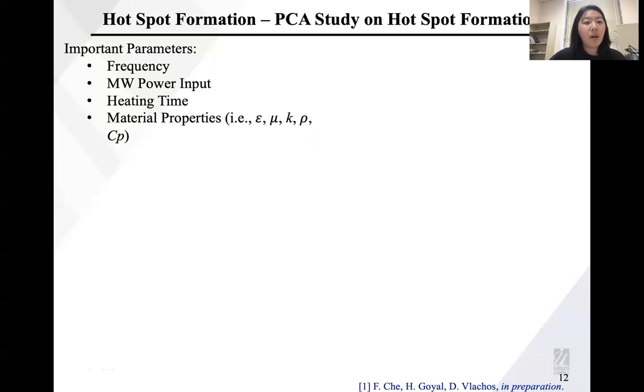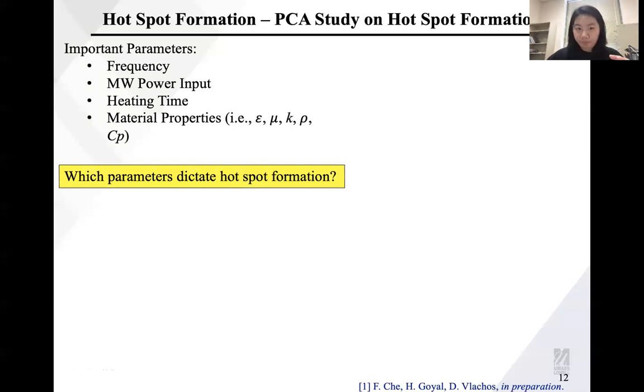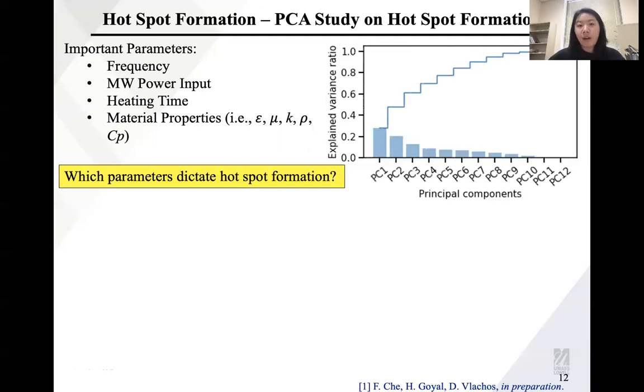Then the next part we want to know is what factors can lead to this hotspot formation. So we tested different parameters such as microwave frequency, microwave power, the heating time of the microwave, and the material properties you are heating, such as the dielectric constant, the thermal conductivity, the density, and the heat capacity. And we had the question, which parameter can dictate the hotspot formation. We did principal component analysis using all the data we generated from COMSOL Multiphysics. And from PCA, PC1 should be the most important dominant factor dictating the hotspot formation.